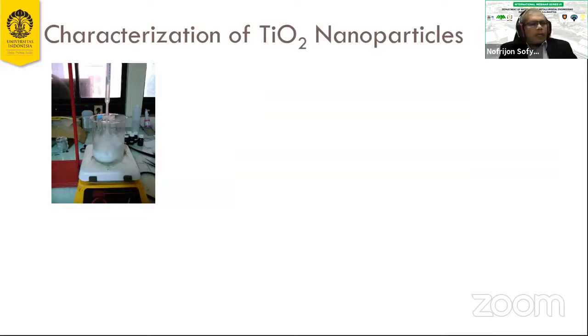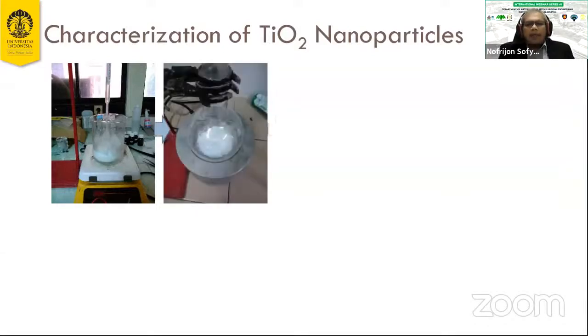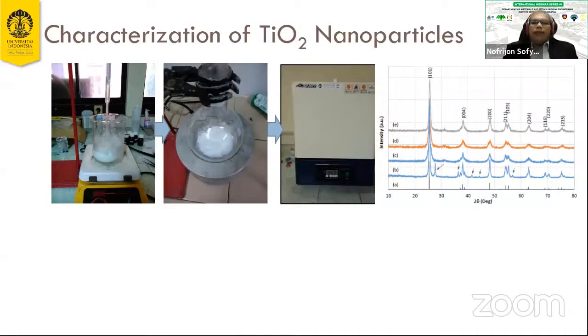So we do synthesize from the purified mineral that we took from our local mineral. We start with titanium dioxide nanoparticles. By using known methods, for example reflux and hydrothermal, we synthesize the titanium dioxide nanoparticle, and we characterize it using X-ray diffraction. We compare the peak that we obtain from our synthesis and the one from the commercial one. A is a reference, B is the commercial one, and C, D, and E are the different methods that we apply.